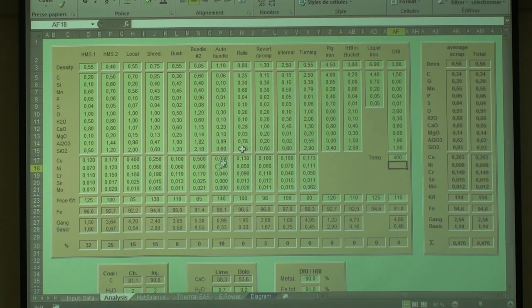For example, when I started in the 90s, the scrap density of the HMS1 used to be 0.7. Nowadays, it's 0.6 or even 0.55. The density has decreased quite a lot. In these days, 0.3 is common. In Dong Steel also 0.3 or 0.36, and South Asia is obviously 0.3. They use the light scrap only. They do not have the heavy scraps. And also in Japan, they did not get the H1, H2 class of the scrap. They use the light scrap only.